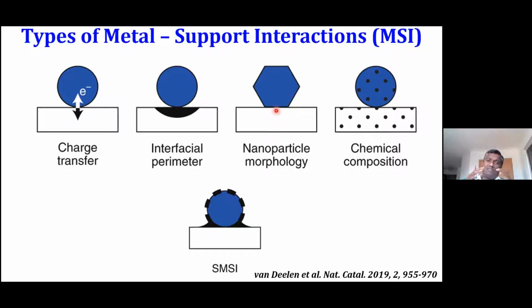In some cases, this support material can influence the structure of the nanoparticle itself. And in turn, that can affect the catalytic activity. So that is also possible. Another kind of interaction is that components from the support can interact with the metal nanoparticle during the heat treatment, during the catalyst synthesis, or even during the reaction. They form sort of an intermetallic compound, or the composition of the metal nanoparticle changes because of the components of the support. So that's another kind of interaction between metal and support. And one relatively well-known phenomenon is the strong metal support interaction, which is called SMSI. I will talk briefly about this particular SMSI during the later part of this talk.